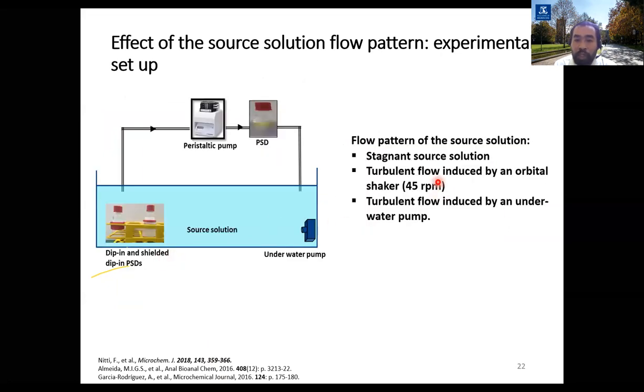So what happened is we chose three different flow pattern conditions. The first one is stagnant water, so the water with no movement at all. The second one is a turbulent flow, which is induced by placing this container containing the source solution on top of an orbital shaker, which was shaken at 45 RPM. We then study the third flow pattern condition, which is a turbulent flow induced by placing an underwater pump. This is a typical aquarium pump that is used to induce the flow pattern of our water condition.